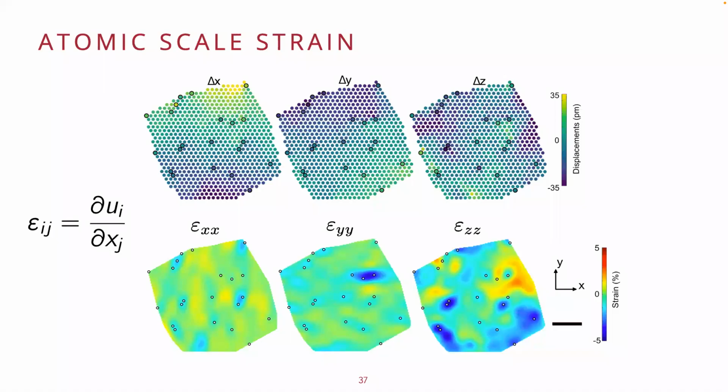Because we have this picometer accuracy, we can actually start to look at what you'll see is that close to our rhenium atoms, we see the most amount of strain, not only in the X and the Y directions, but also in the Z plane. This is really the unique part about our atomic electron tomography: we get true three-dimensional atomic level strains that you normally wouldn't get.